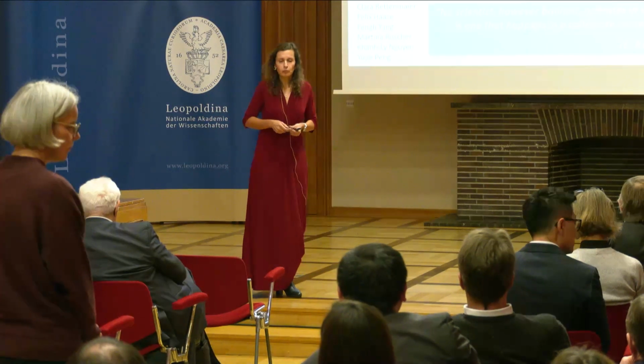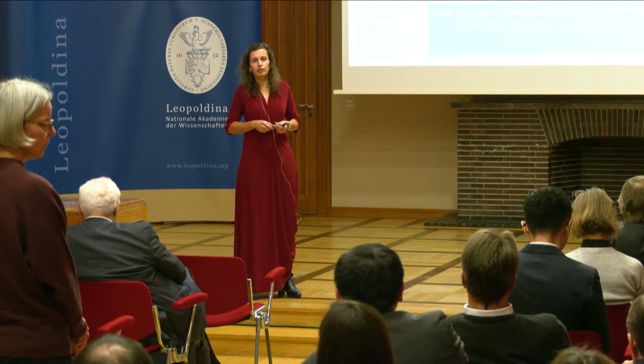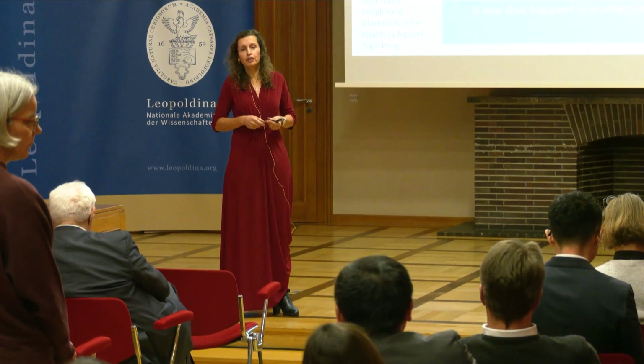Depends on the system. We have not been trying to get record low onset potential. We have been trying to understand what is the origin of the changes. In many cases, people are reporting these record onset potentials under conditions that are completely irrelevant to any industrial application, or they are reporting it for very short periods of time. And so you want to see how this changes. So yes, we have this type of measurements. My focus has not been on the optimization of the onset potential, more on the understanding of what I need to do in the material and in the reaction conditions to get more stability and also more activity.